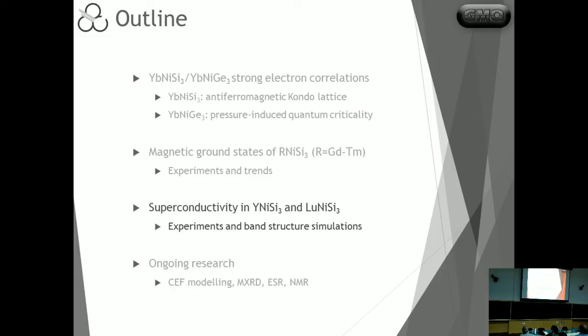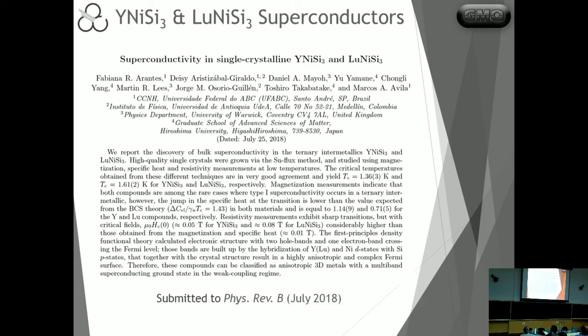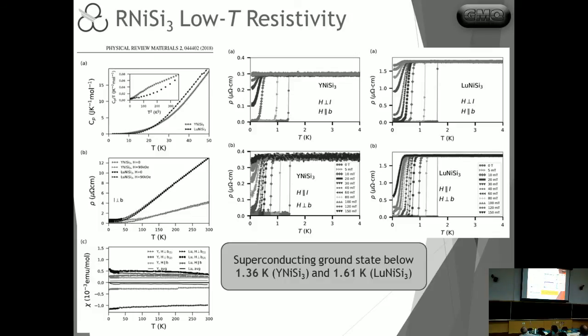Then we looked at the non-magnetic ones, and as icing on the cake, we were rewarded with some new superconductors here. This paper was just submitted a couple of weeks ago. Again, I want to acknowledge Fabiana, who was the postdoc, and Daisy, working on that. This was done in Hiroshima, as Fabiana went back there together with Takabatake to use the low temperature equipment, because we could go down to 2 Kelvin. We were using yttrium and lutetium as the non-magnetic references for the magnetic ones.